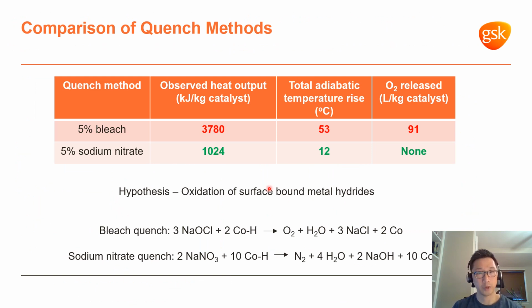So when we compare the numbers for each quench, we see that the sodium nitrate quench produces about 4-fold less heat per kilogram of catalyst, which equates to an over 4-fold reduction in the total adiabatic temperature rise, and this value of 12 degrees is well within the safety limits. We also see that the sodium nitrate quench produces very little gas and no oxygen.